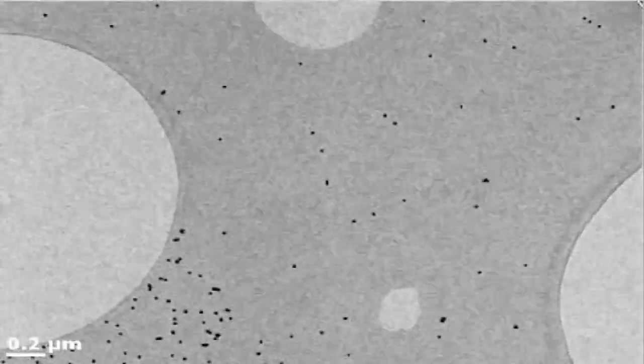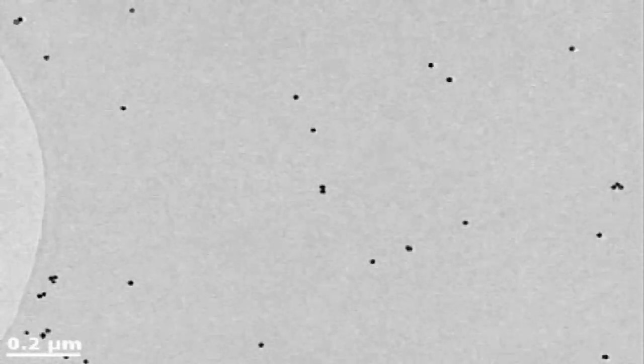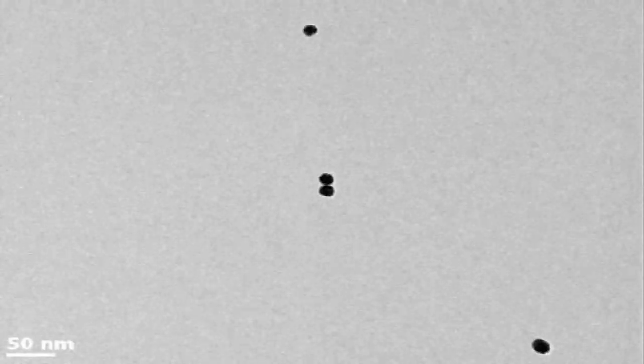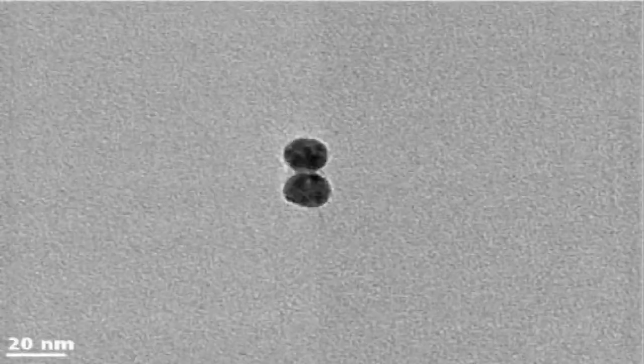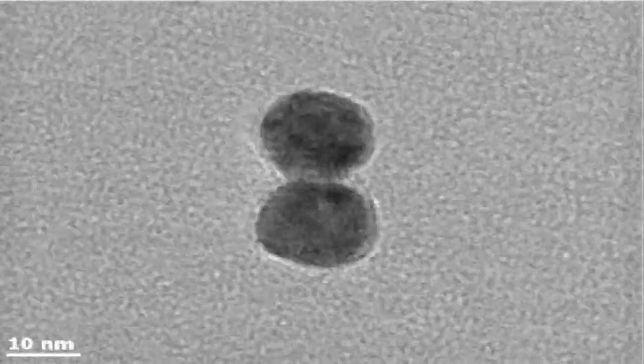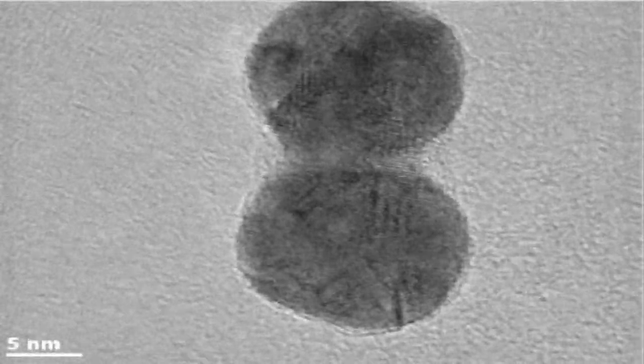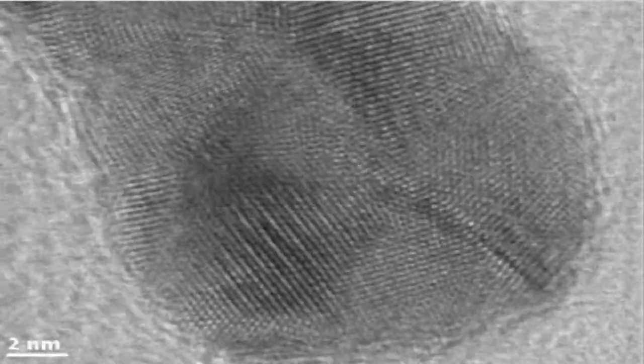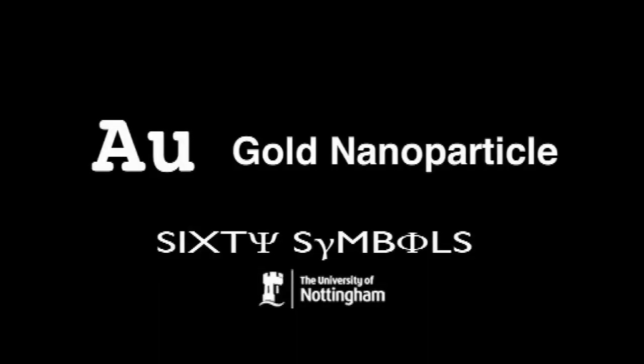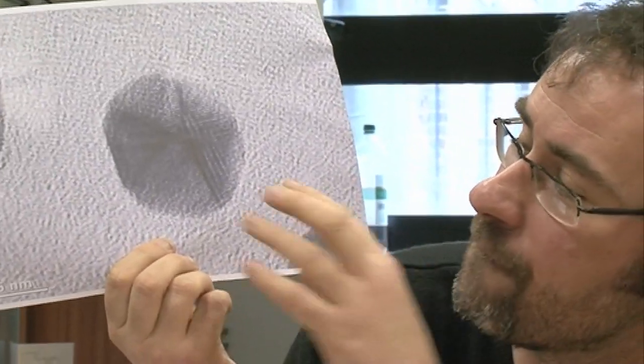We take a little droplet of this solution, we put it onto a grid, we let the solvent evaporate, and then we put the sample into the microscope, and we can see the individual particles. It's a single gold nanoparticle. A tiny, tiny chunk of gold, in this case containing about 125,000 atoms. And we can see the faces on this. We sometimes call it a chunk or a nanoparticle, but it's actually better described in this case as a nanocrystal.